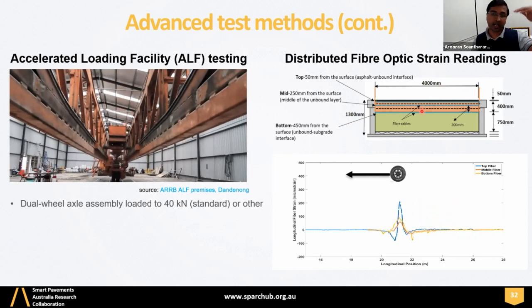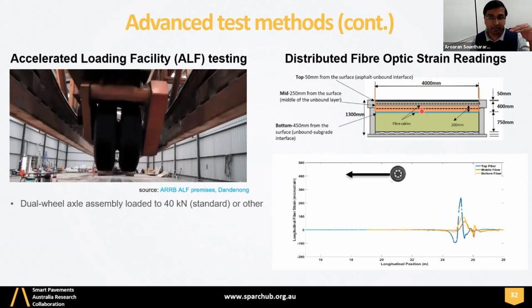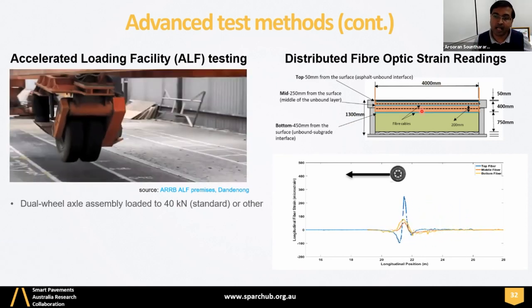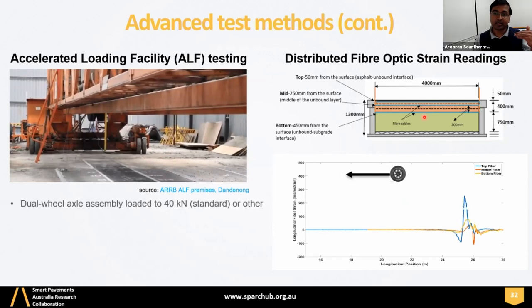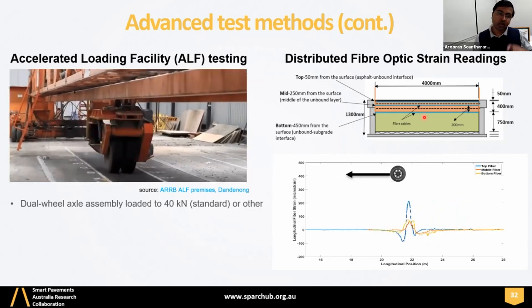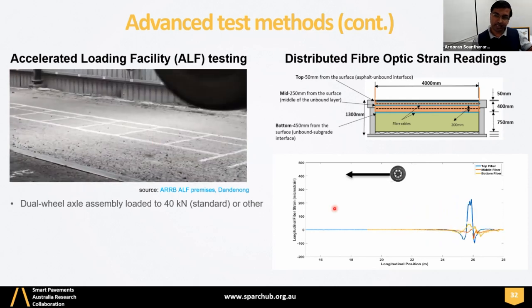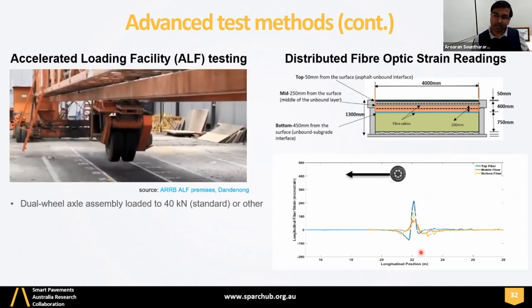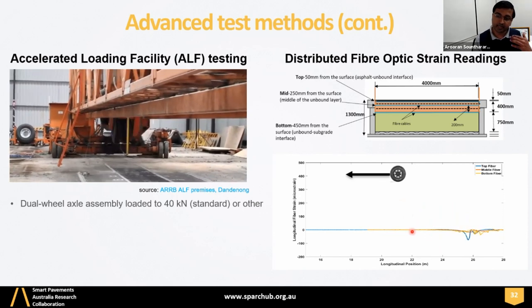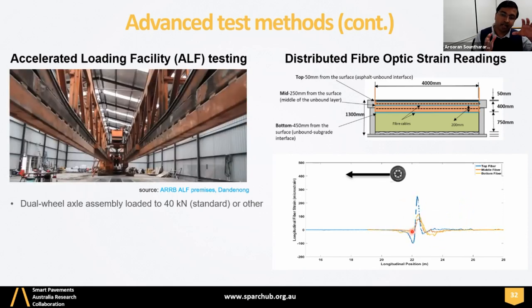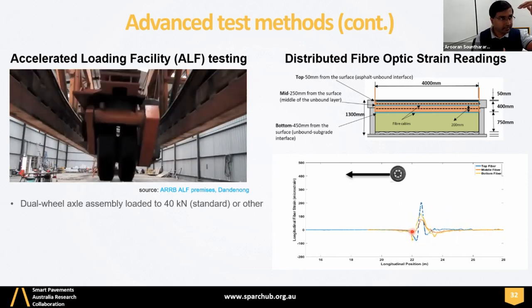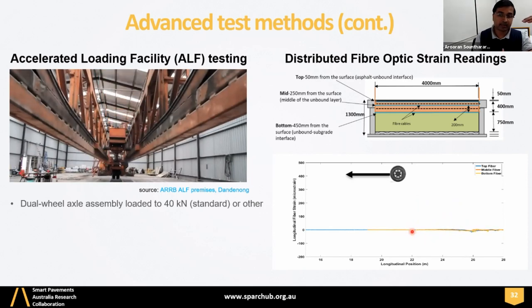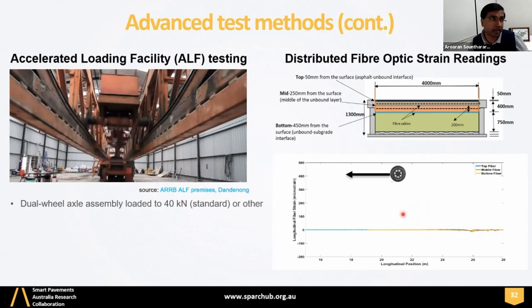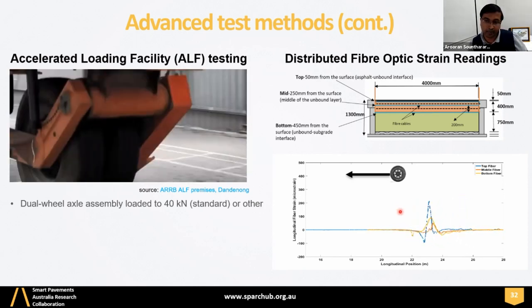One is at the top, right below the seal, and another one is in the middle of the unbound layer. This is an unbound layer, middle of the unbound crush rock layer, and the last one is in the subgrade, right? So as this wheel moves on the surface, you see the fiber optic strain measurements on the bottom graph. It's a graphic illustration. So as the wheel moves, right, the top fiber receives the most significant strain because it's very close to the surface, and as depth increases, the strain coming to the pavement decreases, right? As captured by the distributed fiber optic strain measurements.